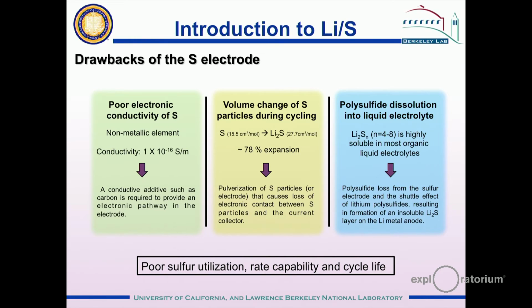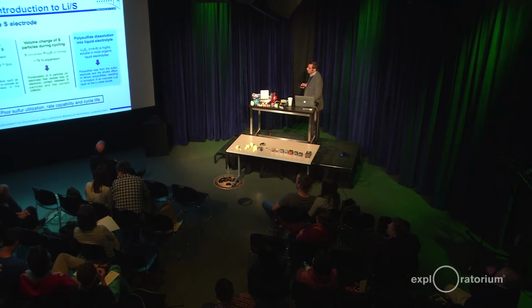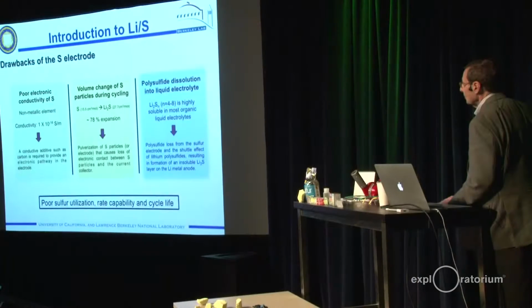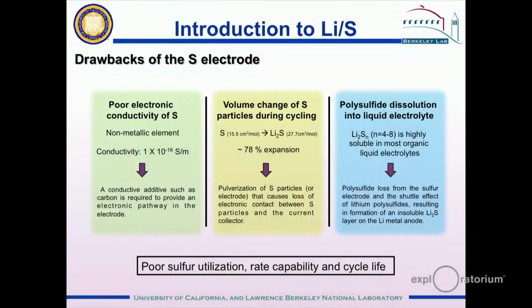Another difficulty associated with the chemistry of sulfur is that during the discharge reaction you can form polysulfides, which means various numbers of sulfur combined with 2 lithium atoms to make a lithium polysulfide. These lithium polysulfides are soluble in organic solvent-based electrolytes, and that means that the lithium polysulfide can dissolve in the electrolyte and move away from the electrode, and that represents a loss of capacity of the cell. So we use electrolytes which have very low solubility for the polysulfides.